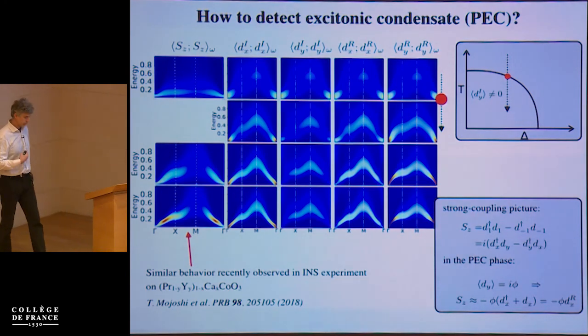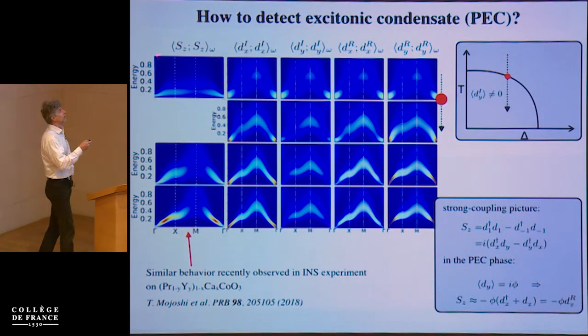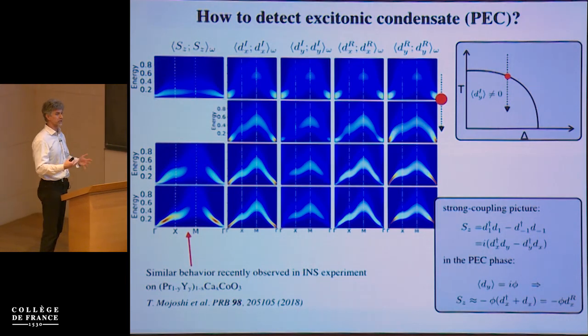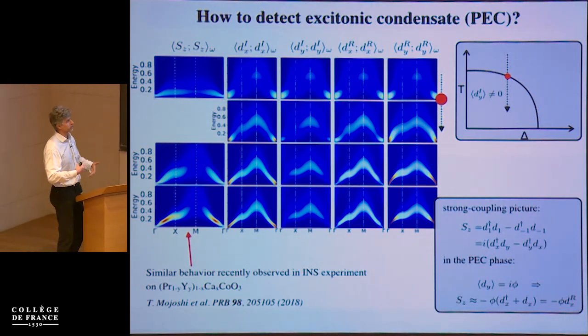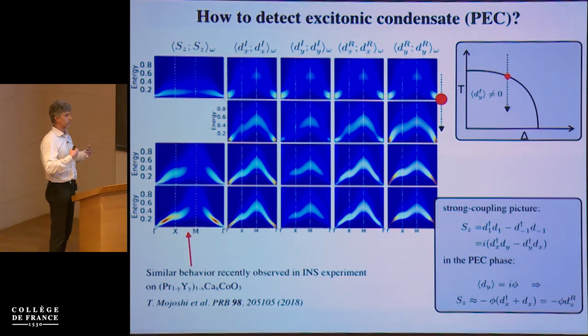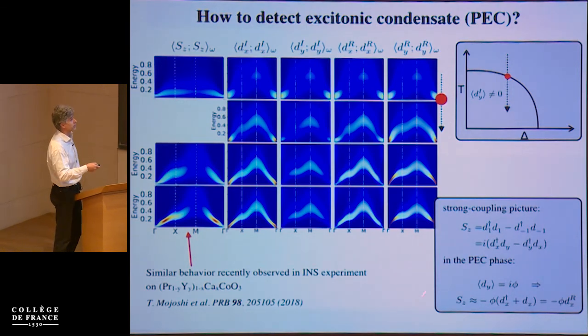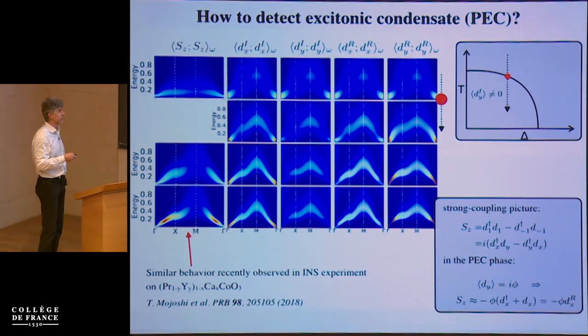So we propose that a spin structure factor, which can be easily measured with inelastic neutron scattering, can actually bring us proof of at least this polar excitonic condensation taking place.